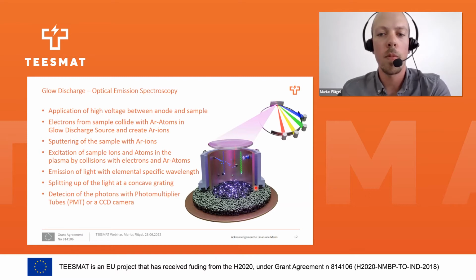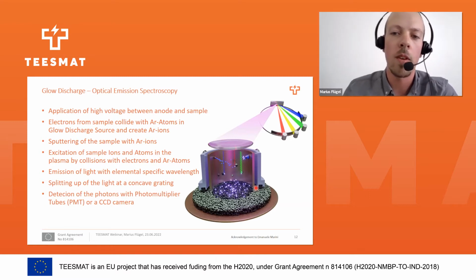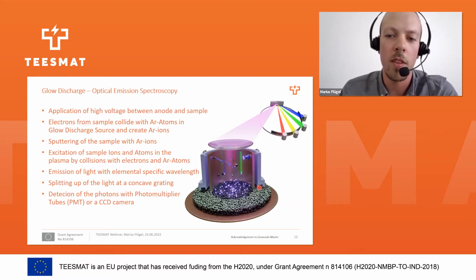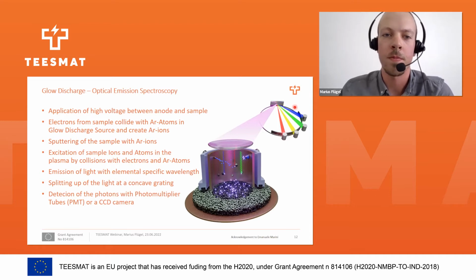Those sample atoms then diffuse into the plasma, where they collide with argon atoms and electrons, and are electronically excited during the collision. During de-excitation, they emit light with a specific wavelength, which is then focused onto a concave grating and split into its individual components, which is then detected by photomultiplier tubes or a CCD camera.